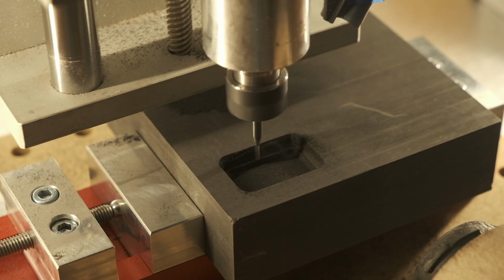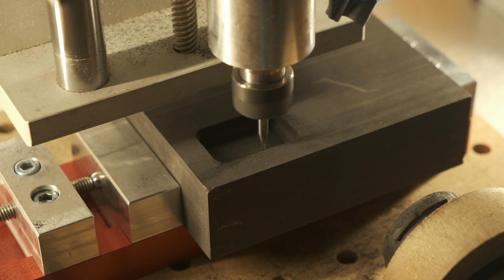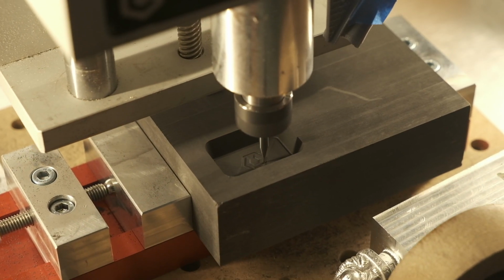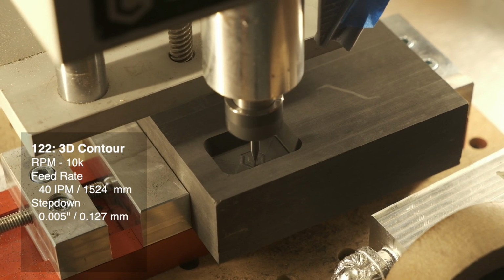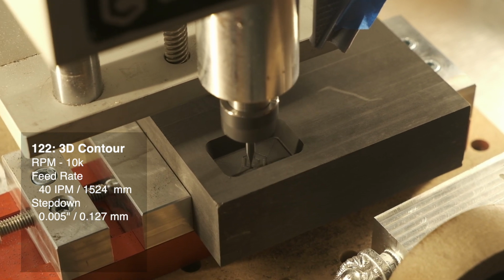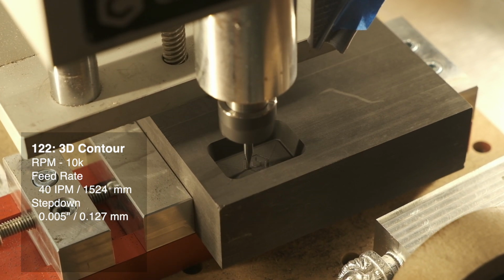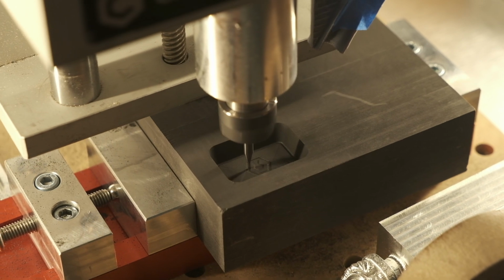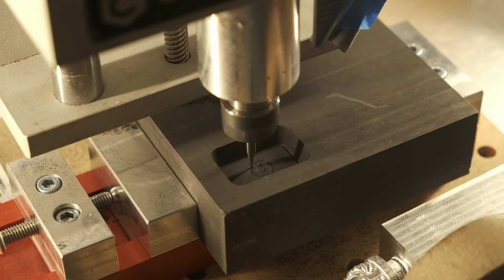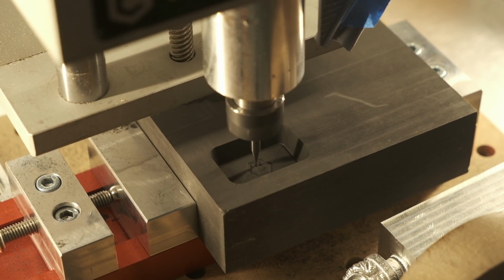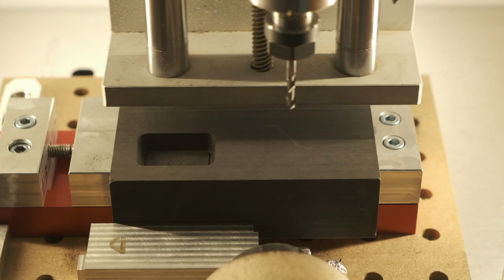So don't try translating this directly to a pocketing toolpath. And lastly, the 1/32 inch flat end mill, 10,000 RPM, 40 inches per minute, 5 thou step down. I'm using this toolpath in place of a pencil toolpath because I understand its parameters a little better. It's just here to define the features with a little more resolution. Alright, that's one mold down.